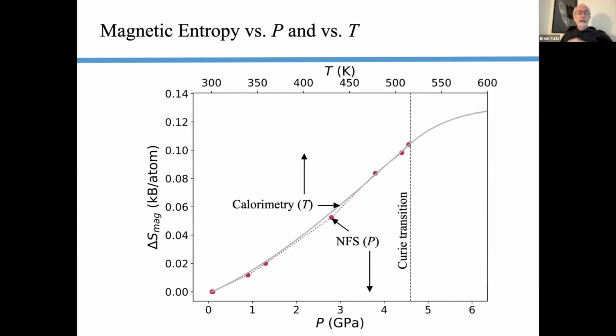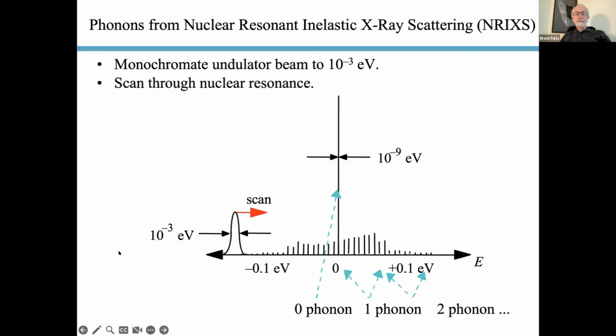So here's what we get. Here's how the change in magnetic entropy changes with pressure. The reference point is 0. It's not really 0. And up to the Curie transition, both the calorimetric entropy by temperature and the nuclear forward scattering by pressure are in pretty good agreement. Maybe there's a little more curvature for the nuclear forward scattering.